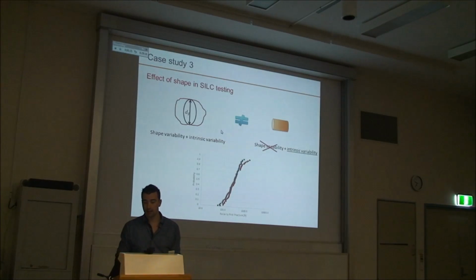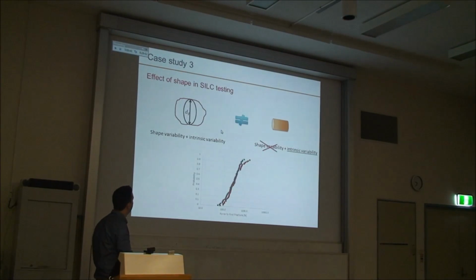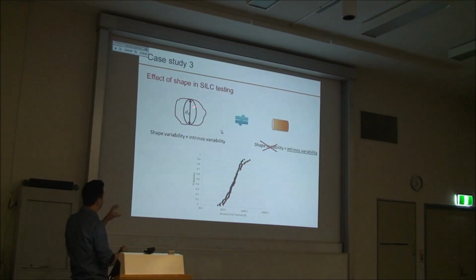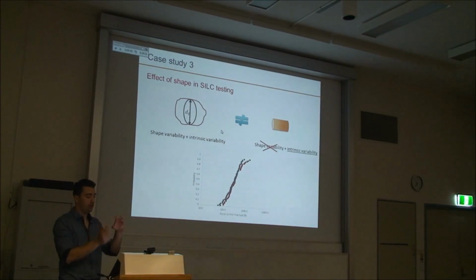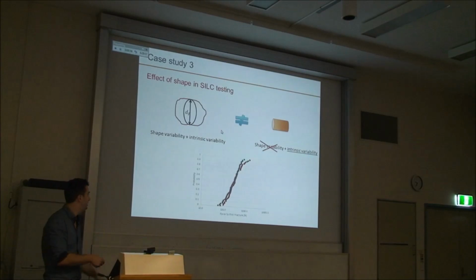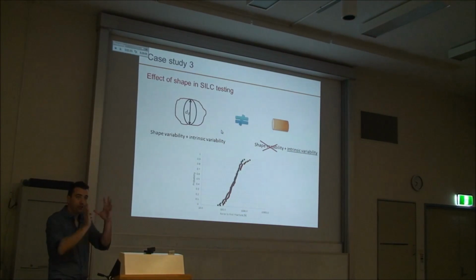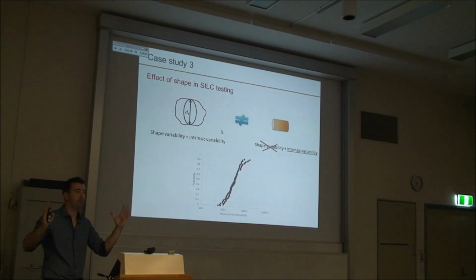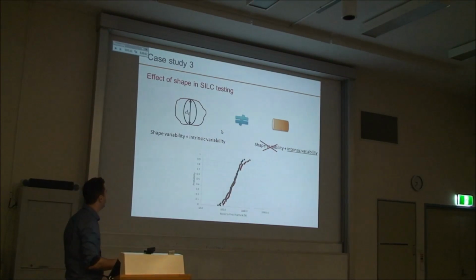So then we said, well, some of the variability that we can observe here is due to the shape. On the left side here is just a roughly spherical particle, but it's got rough corners and rough geometry, and that can increase the variability that we observe. So we said, if we have a control shape like this cylinder, can we steepen that distribution, make it steeper, so the two distributions will be different and we can statistically differentiate them? Okay, so this is the motivation behind looking at the shape and wanting to test regular shapes.